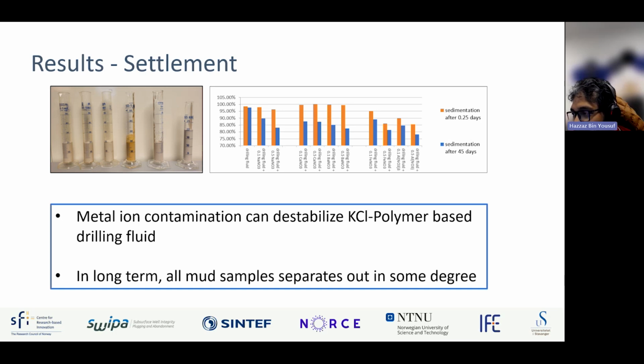The other monovalent and divalent ions don't have that immediate effect. However, if we keep this for about 45 days, as you can see from the chart, the other ions can also destabilize the drilling fluid in the long run.